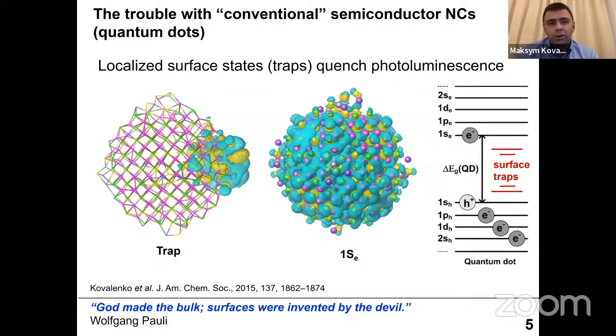What was also not so exciting from the beginning was to notice that the light emissive property of this quantum dot was not that great at all. The problem back then was that quantum dots as produced do not exhibit bright luminescence. And luminescence, as you know, is a reversal of the absorption, right? So that the photo-generated electron hole pair recombines back. The big hope for these materials was that they would emit light with high luminescence quantum efficiency, and therefore they could be used as inorganic nano-sized light emitters. But they turned out to be very bad light emitters as produced.